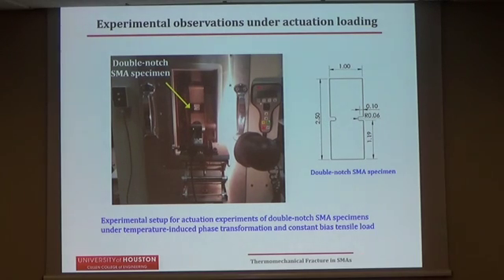So we tested double-notched specimens, thin SMA bones, like this. And the loading paths that we applied are as follows. What we did is we first heated the material. We made sure that it is in the austenitic phase. Then we applied a mechanical load that was just a fraction of the load needed for failure at that temperature. And then we cooled down the material. And what happened? The material fractured.